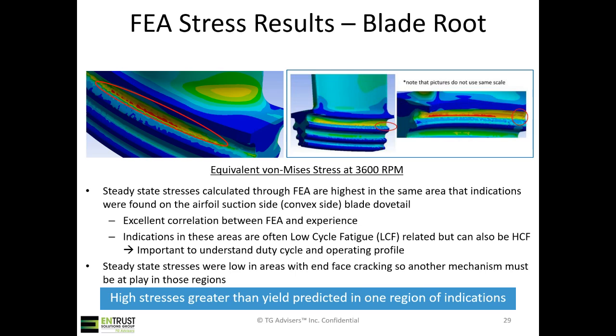So ultimately, we found that steady state stresses calculated through the FEA are highest in the same area that indications were found on the airfoil suction side, the convex side. I think I said concave side earlier. That was just a mispronunciation. It was the convex side or the suction side of the blade dovetail. So this helps us ground our model. We have excellent correlation between the FEA and the experience, but then we also need to still find out why there are cracks in the end faces.